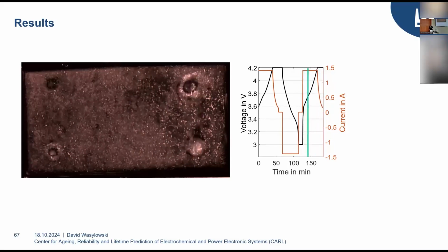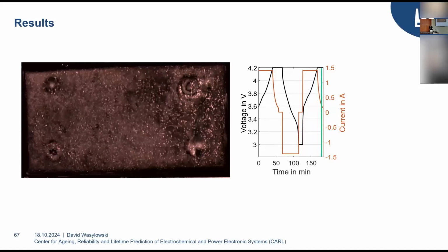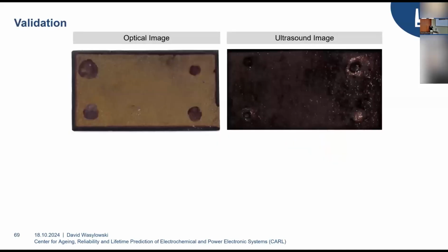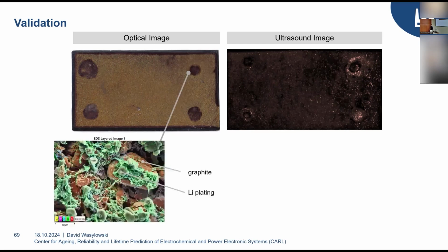And again, we need to verify whether this is actually lithium plating that we're seeing here in our ultrasound image. And again, we disassemble the cell, we compare the optical image to the ultrasound image and get again this visual congruency. But in order to verify that there is actually lithium plating happening here, we again made this scanning electron microscopy image, which again verified that there is actually metallic lithium being plated only on the perimeter of this adhesive and not anywhere else within the battery.